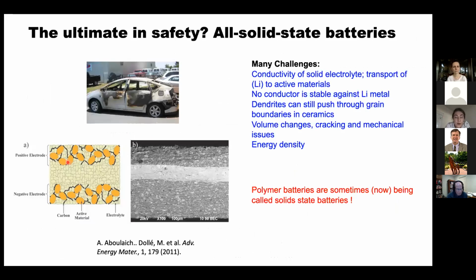And then finally, just in the sort of overview, the ultimate in safety is to forget the liquid electrolyte and make it all solid. And this is a spark plasma sintered battery made by Michael Dolle and his group. The cathode is here. This is the solid electrolyte. This is the anode. And you can just see the challenges of getting the lithium through these highly resistive things with multiple grain boundaries, and each of these materials, when you're pulling the lithiums in and out, will expand and contract, and so the potential problems for fracture and failure are significant, but an important area to work on.